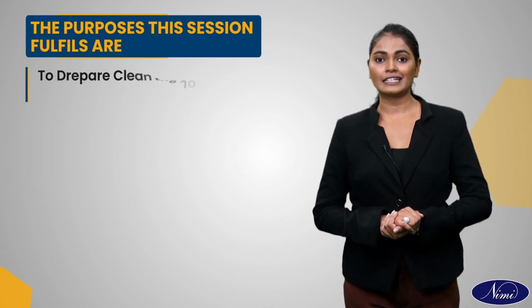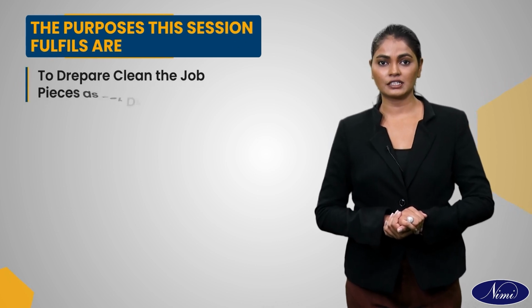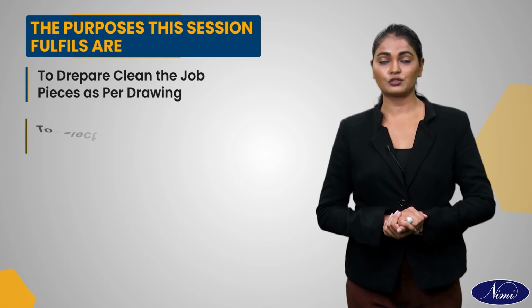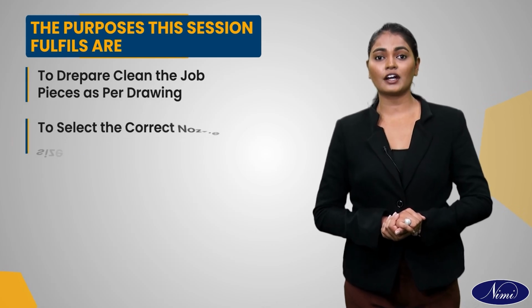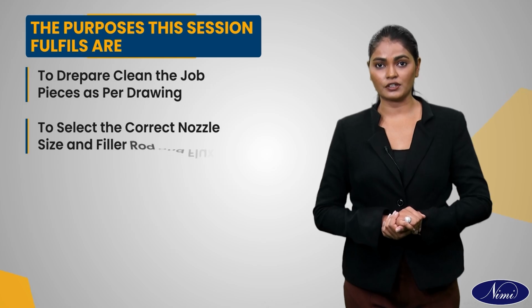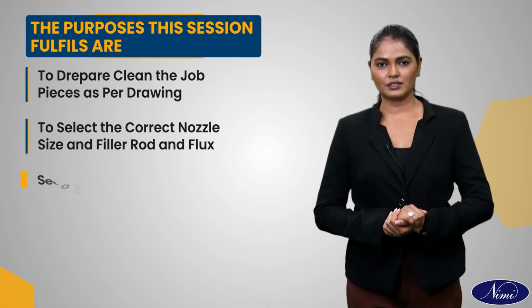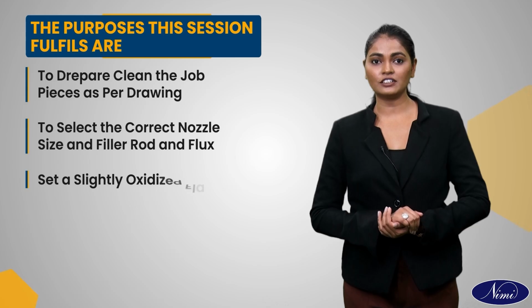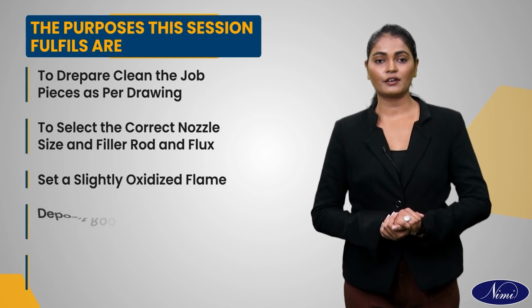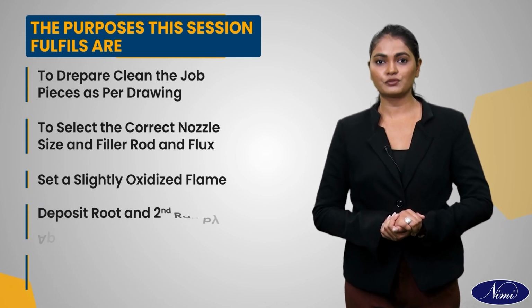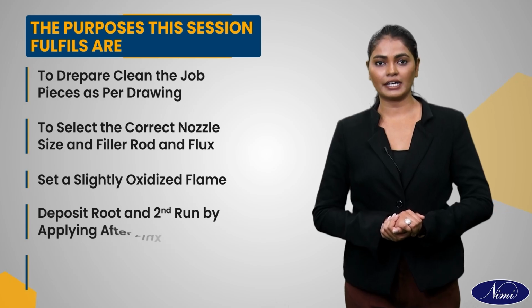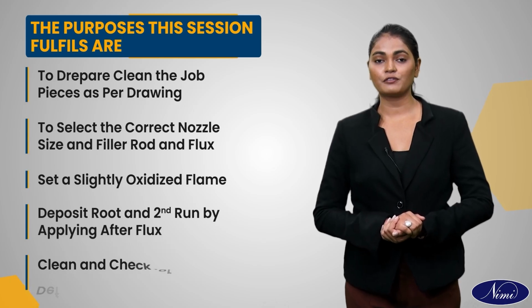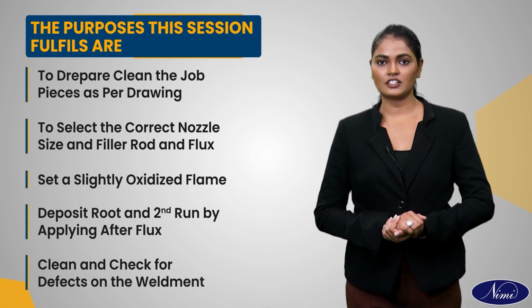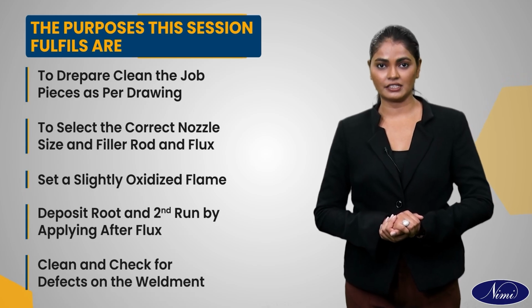The purposes this session fulfills are: 1. To prepare and clean the job pieces as per drawing. 2. To select the correct nozzle size, filler rods and flux. 3. Set a slightly oxidized flame. 4. Deposit root and second run by applying the flux. 5. Clean and check for defects on the weldment.